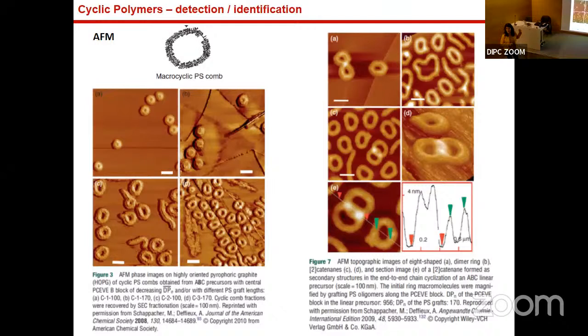Let's go to the detection and identification. How do we know that we get cyclic polymer? It's very important for a chemist. Imagine, of course, these are AFM pictures, but it's not easy, and we cannot image all the cyclic polymers. Why? Because in this case, this is a copolymer, where the cyclic polymer is made by another polymer, and the comb, or the brushes, are polystyrene. In this sense, the walls of this cyclic chain become thicker, and can be analyzed by AFM. But normally, polymers are not so thick and cannot be measured by AFM.